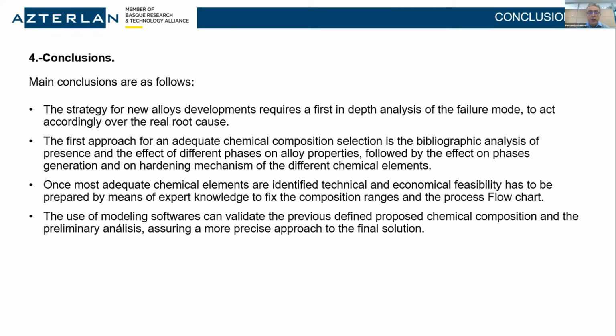But in general, let's say that the strategy for new alloys development requires, first, an in-depth analysis of the failure mode to act accordingly over the real root cause. The first approach for an adequate chemical composition selection is the bibliographic analysis of the presence and the effect of different phases on alloy properties, followed by the effect on phases generation and on hardening mechanisms of the different chemical elements. Once the most adequate chemical elements are identified, technical and economical feasibility has to be prepared by means of expert knowledge to fix the composition ranges and the process flow chart. And finally, the use of modeling software can validate the previously defined proposed chemical compositions and preliminary analysis, assuring a more precise approach to the final solution.